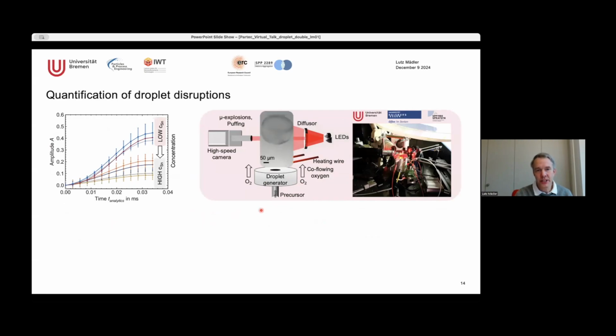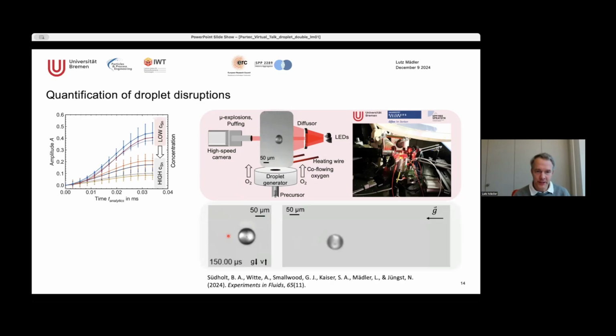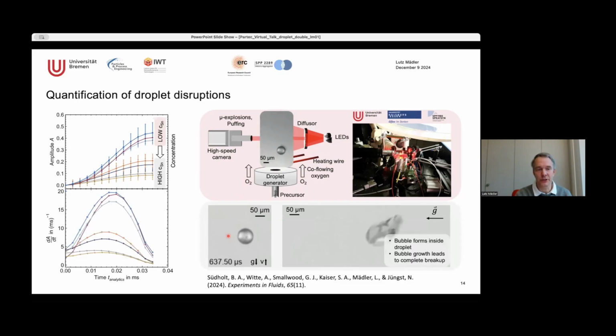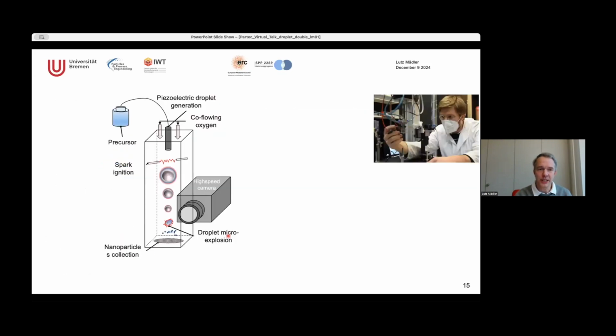And then what we see actually, and you saw it here in the video, is that there's a vapor bubble forming, and this vapor bubble is growing. This is because the surface of these droplets gets blocked, and there's no more evaporation. And then the droplet heats up internally and starts boiling. And that's what leads to these droplet explosions. But the question is, is that important for our materials or not? And this is what Jan can answer here in his experiment.